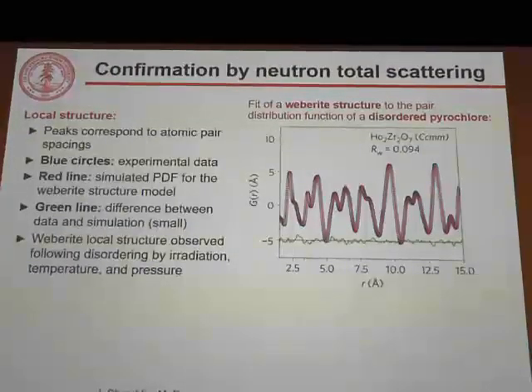We've confirmed these results using neutron total scattering, so I show here a pair distribution function resulting from those measurements, where peaks correspond to local atomic pair spacing. So again, this tells us the local coordination structure.